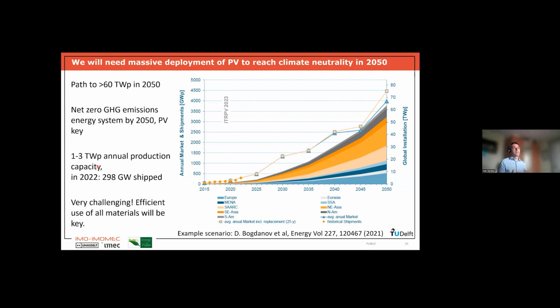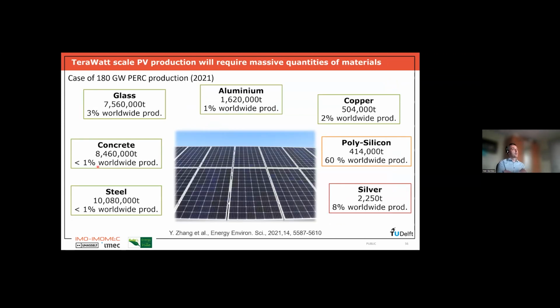So that means the annual production needs to increase probably by a factor of 10 in the coming years and decades. And this is very challenging, especially from a material point of view. And this is shown here. If we go to 2021, we can say that we produced around 180 gigawatt of PERC solar cells. And here you see, taken from this paper, the quantity of materials that were needed for this 180 gigawatt PERC production. So we have steel and concrete, that is just for the mounting structures of the systems. We have glass, of course, we have aluminum, copper, polysilicon and the silicon material itself, and we have silver. So you see here in absolute value the amount of tons of material that we needed for 180 gigawatts of PERC installations.